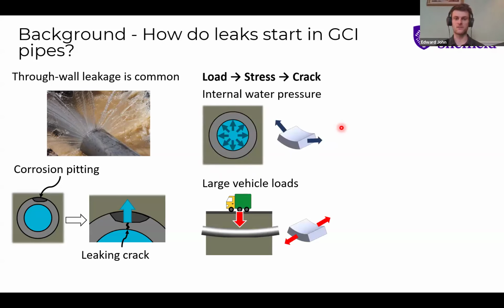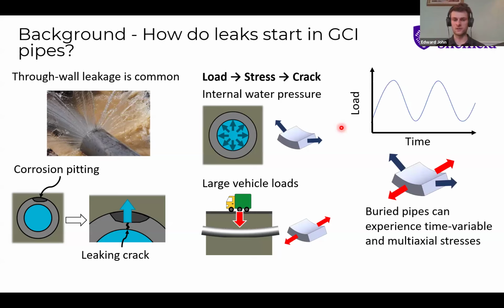Two that I wanted to mention specifically were internal water pressure loading, which effectively all pipes experience, and this tends to create a stress acting circumferentially around the pipe, so in the hoop direction. And another particularly interesting one is large vehicle loads. For smaller pipes, these can cause bending loads, and this mainly causes stresses acting in the axial direction, so along the pipe. Both of these loads can cycle multiple times per day, so this creates the possibility of fatigue cracks forming. This is a crack that forms gradually over time rather than in a single sudden overload.